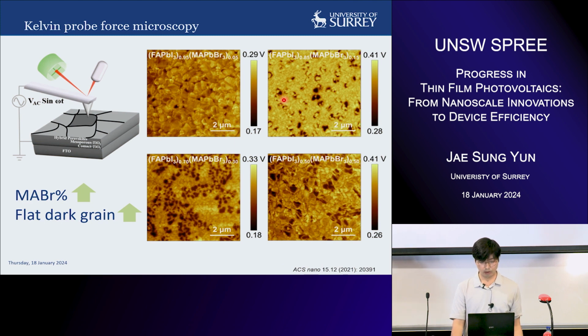So we measured Kelvin force microscopy, which measures the work function distribution of your material. And interestingly, what we observe is that unlike the grain shapes and grain size are sort of comparable, we can see that there are regions where they have a very high work function. So you can see that some of the grains in here have different work function compared to the other area. And these sort of abnormal grains, number of abnormal grains increases if we put more bromide into your material.